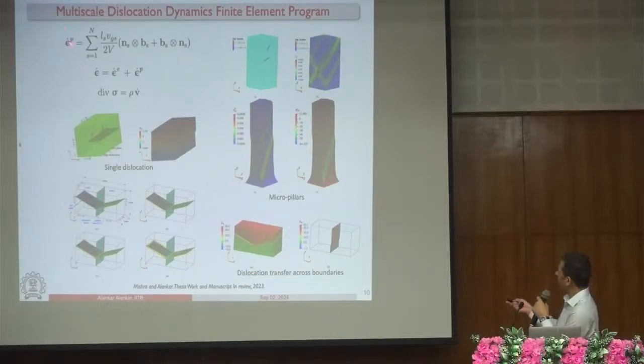In this, we capture how much slip is happening on every slip system, or total slip which is happening on all the slip systems, by measuring what type of dislocations exist. This is LS, the total dislocation line length on slip system. What is the velocity of those dislocations? What is the geometry of the slip systems on which they are moving? Right? And by doing all those calculations, we know what is the rate of plasticity in the single crystal where we have this pool of dislocation, right? And by arranging all this and solving it iteratively, numerically, we are able to do very nice studies. For example, we can study this behavior of deformation of micropillar that I showed you in the beginning, right?